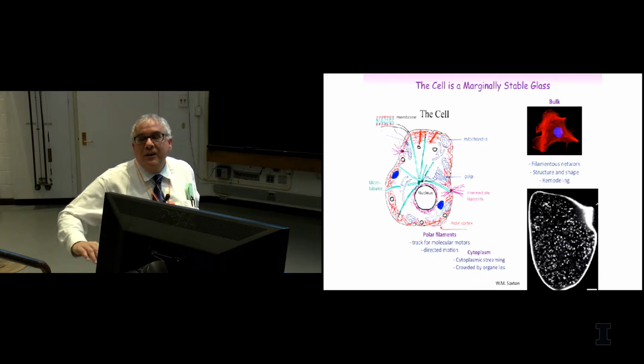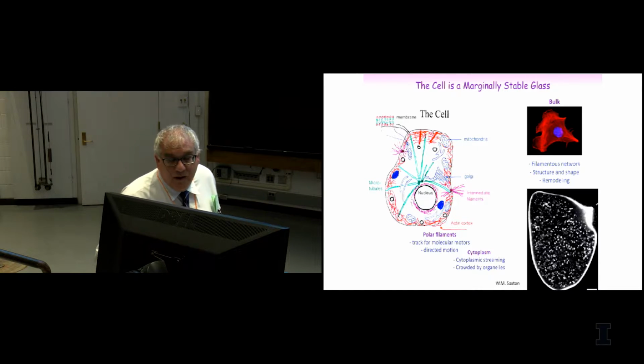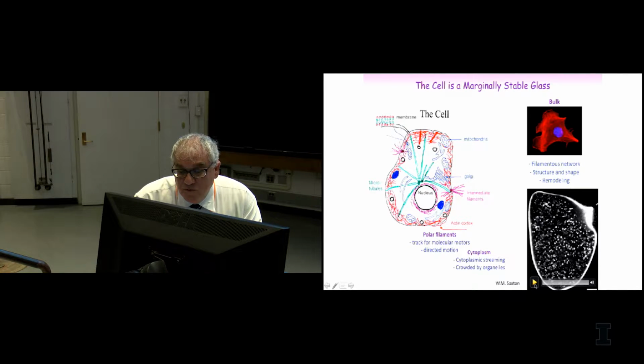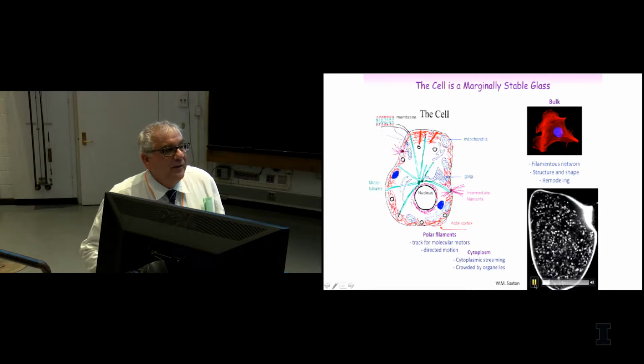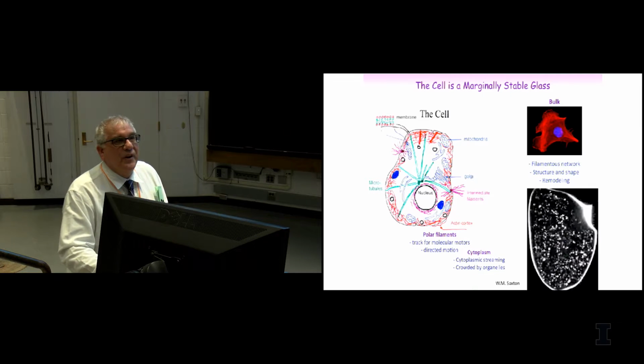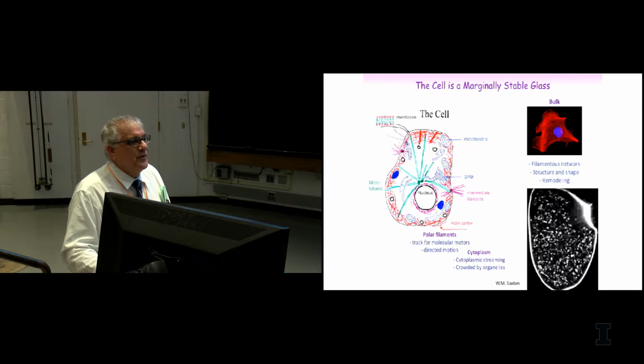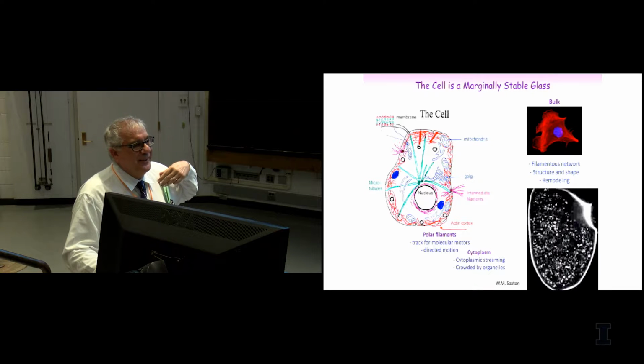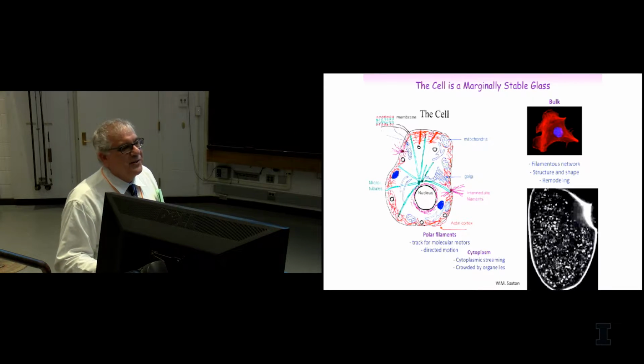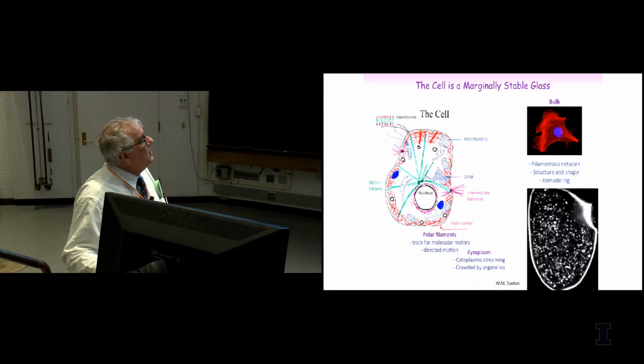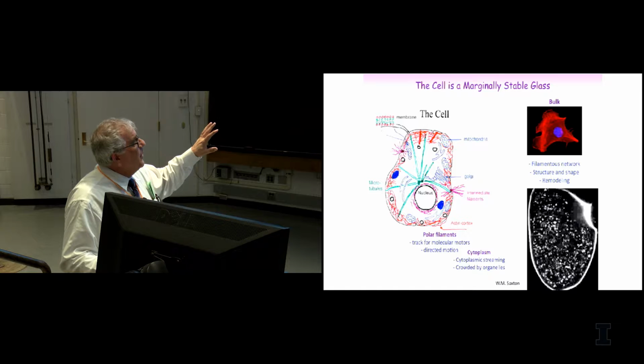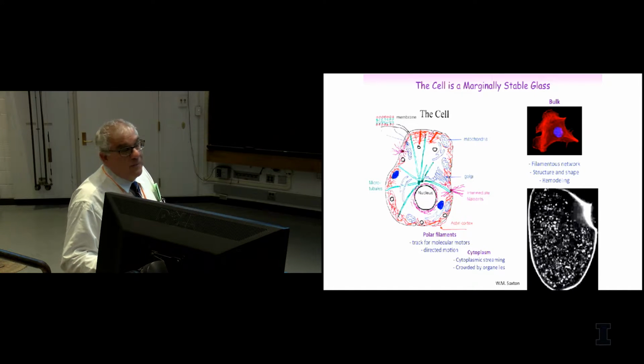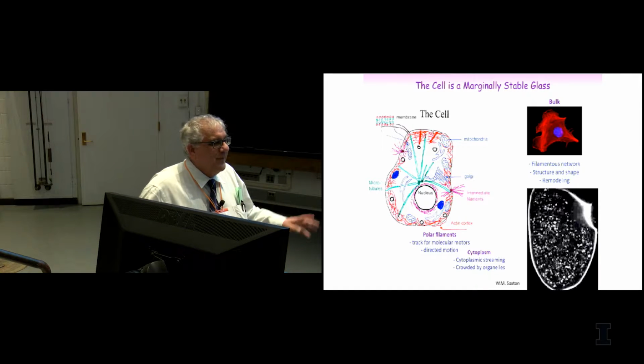The inside of the cell is very likely a marginally stable glass. It has very large objects. Because of their being large in size, they don't move intrinsically very fast, which is why what for a molecular liquid is 1 hour corresponds to a microsecond in this world, or an hour for colloids is really a microsecond relaxation time for cellular things. And so cells really have assemblies of particles in there that are very near to this marginally stable point. And of course, in this sense, this would explain why cytoplasms are indeed more fragile than inorganic glass.